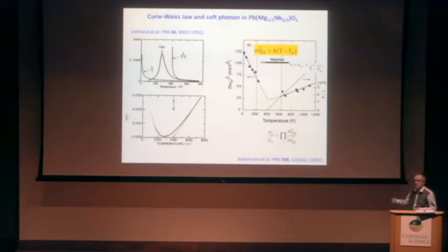And Peter Gehring and Wakimoto studied phonons using inelastic neutron scattering, and they found really phonon softening at high temperatures, and below freezing again some hardening, but in this temperature range there was no proper signal because there is a waterfall effect. I will not speak about it.